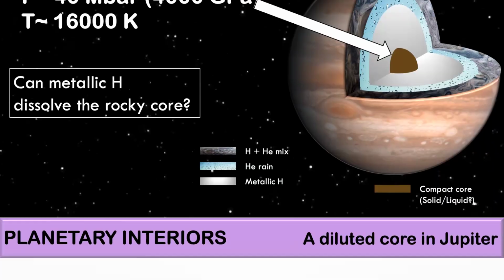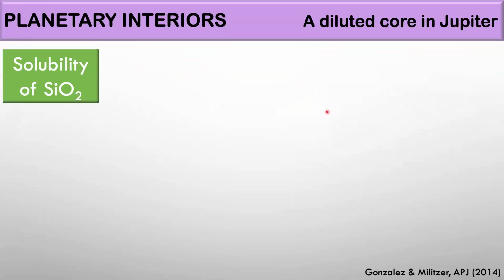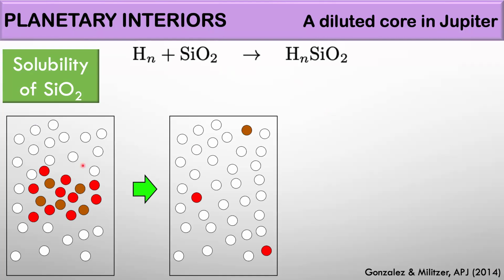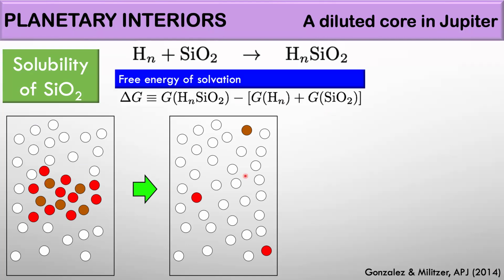So in order to address this question, we basically went to the equations of thermodynamics, and we chose a material, as usual. In this case, it was silica, because we believe it's one of the common rocks to be found there in the core of Jupiter. And we were focused on the following chemical reaction. Can N atoms of hydrogen in the metallic form interact with 1 unit of silica to form a dissolved system of hydrogen and silica? So what I have in mind basically is that silica is surrounded by a lot of these hydrogen atoms in the metallic phase, and they basically dissolve the rock. And then you have to compute what are the energy differences between the original state and the final state. So basically the free energy of solvation.